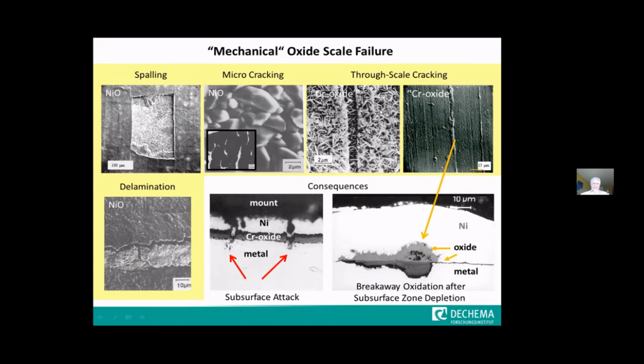In some cases, if the depletion of the subsurface zone by the metal that is needed to make the protective healing has gone too far and not enough of this alloying compound exists anymore, then the oxidation mechanism can switch from protective to non-protective at such a crack. That's something we can see here, and that's called breakaway oxidation.